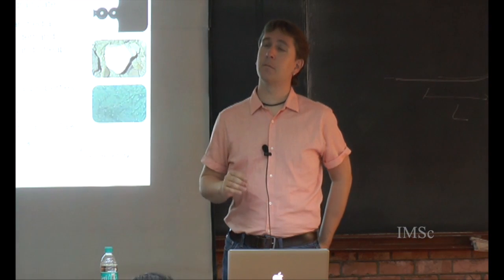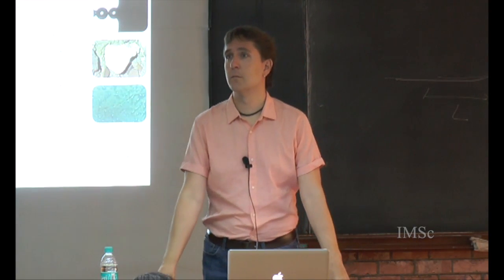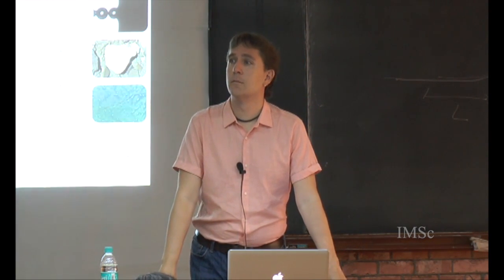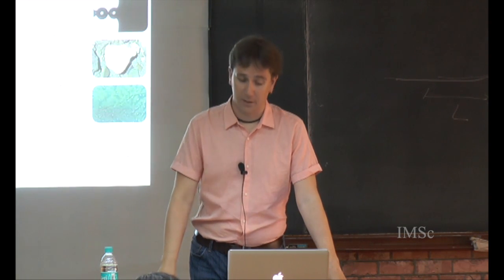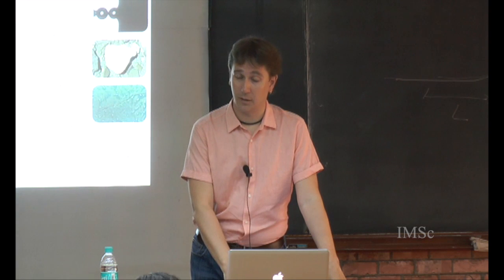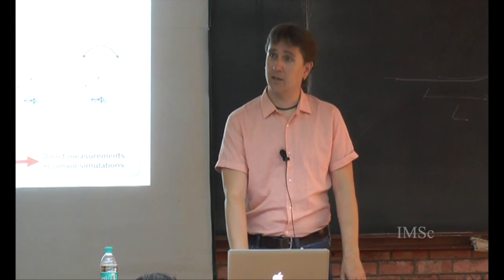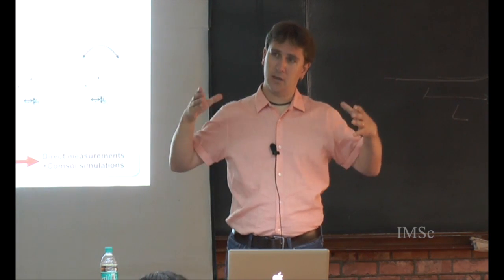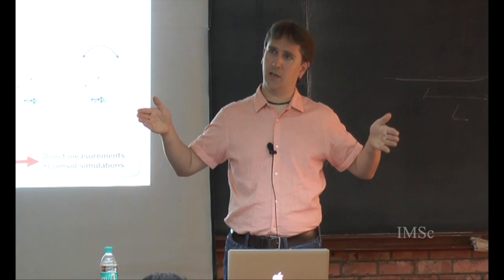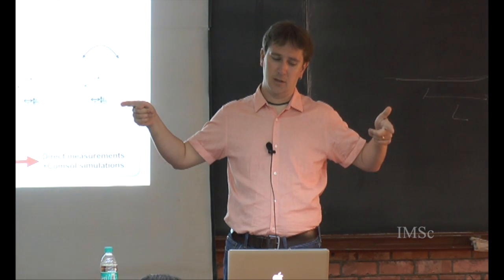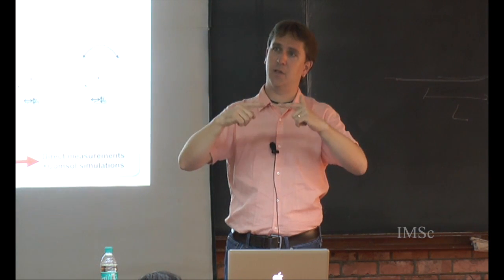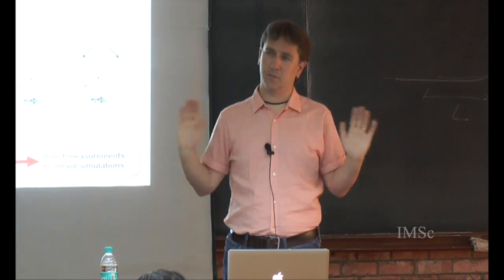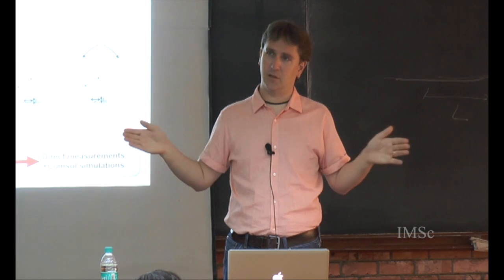As far as I could see from the pictures, these are disordered. Yes, they're random packing. We looked at that. If you look at the edges of the cylinder, there's about 2 layers. If you look at the pair correlation function, there's about 2 layers deep that they are correlated. So there's some wall effects, but the cylinders are large compared to that.